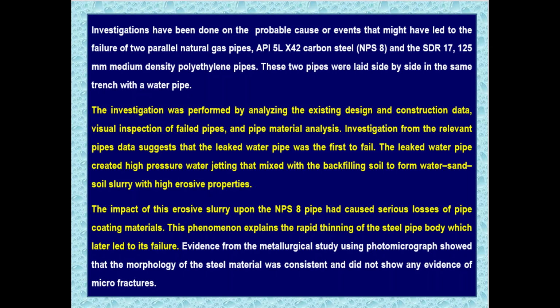Investigation from the relevant pipe data suggests that the leaked water pipe was the first to fail. The leaked water pipe created high pressure water jetting that mixed with the backfilling soil to form a water, sand, soil slurry with high erosion properties. The impact of this erosive slurry upon the NPS 8 pipe caused serious losses of pipe coating materials. This phenomenon explains the rapid thinning of the steel pipe body, which later led to its failure.